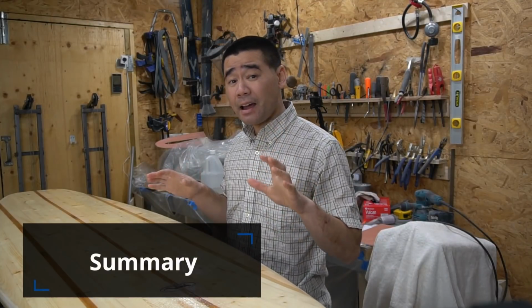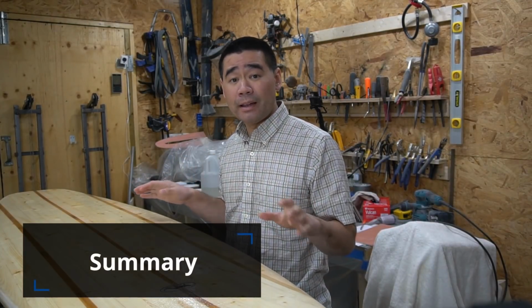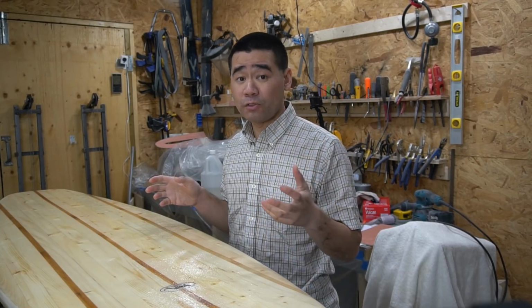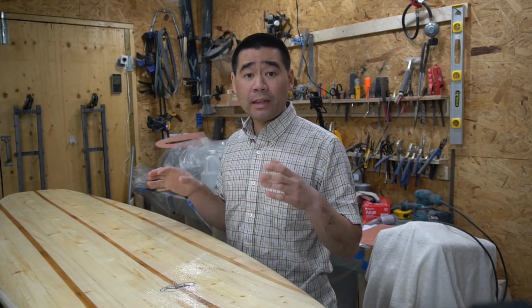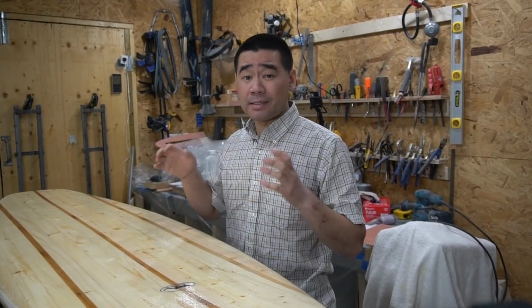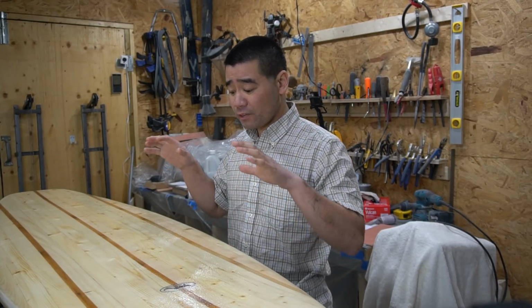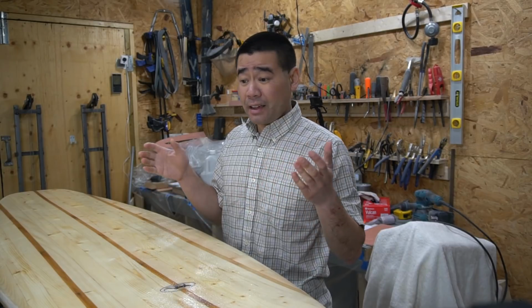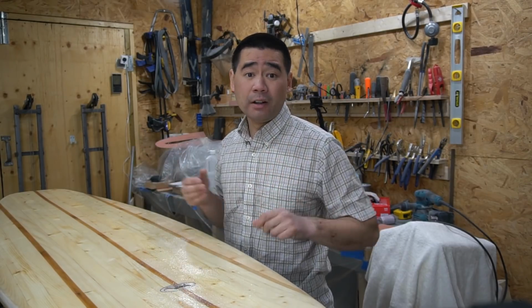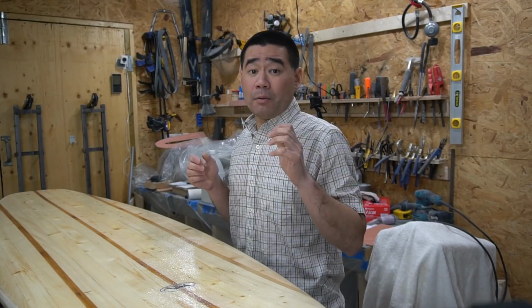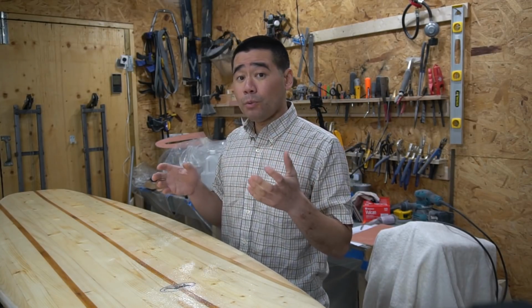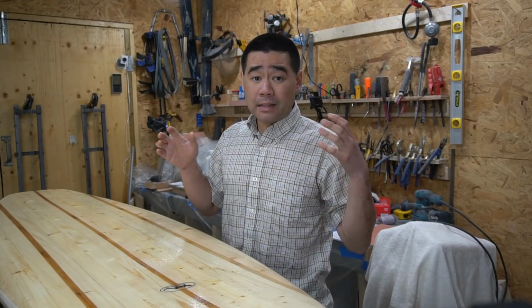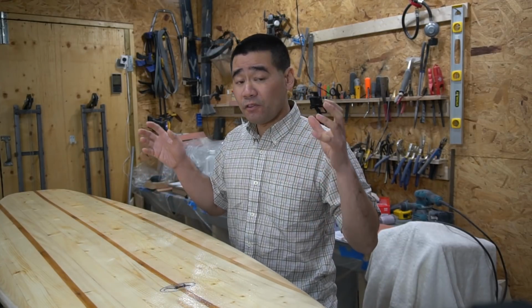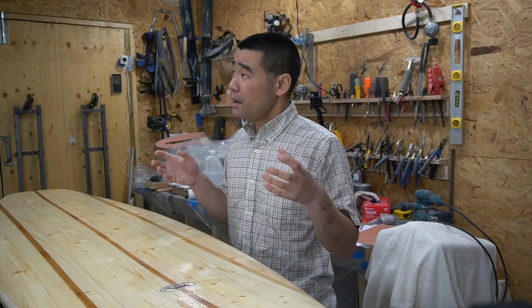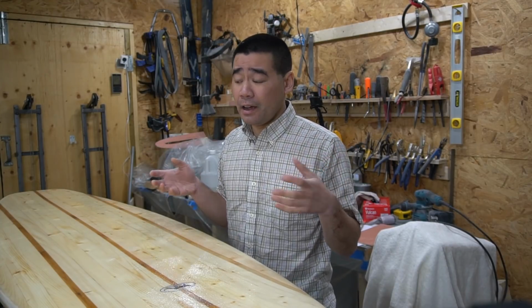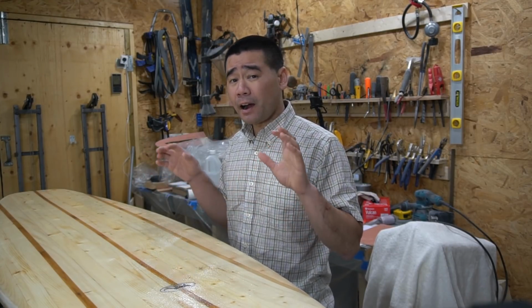Alright, so that is how I glass a wooden surfboard. It's slightly different than glassing a foam surfboard, where with the wooden surfboard you can get away with less overlap on the rails since the wooden board has a bit more inherent strength built into the wood than say a foam board because it's going to be a little bit more spongier. So I'm going to sum a few things up. Remember when glassing to let the room, the surfboard, the epoxy come up to at least 15 degrees Celsius, and ideally maybe even room temperature if you can. Otherwise, the epoxy may not harden properly.